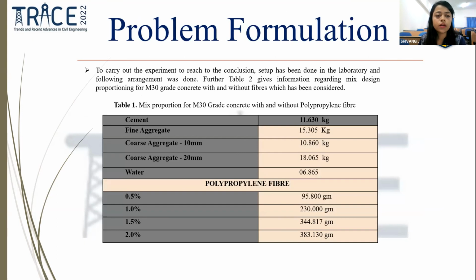Coming to the problem formulation, to carry out the experiment and reach the conclusion, the setup has been done in the laboratory and the following arrangements were made. Further, this table gives the information regarding mix design proportioning for M30 grade concrete with and without fibers. Table 1 demonstrates the mix proportion used for M30 grade concrete with and without polypropylene. For the mix proportion, we have used cement, fine aggregate, coarse aggregate of 10 and 20 mm respectively, and water. After that, we have added polypropylene fiber in 0.5%, 1%, 1.5 and 2 percentages.